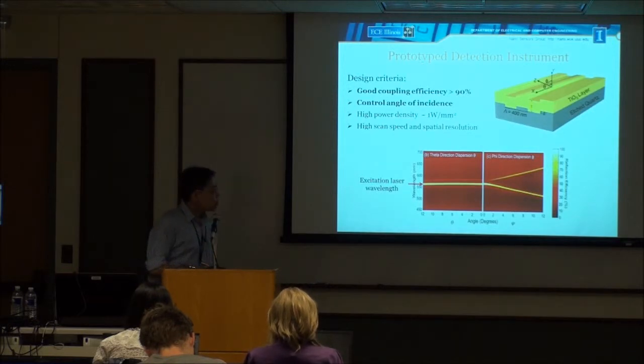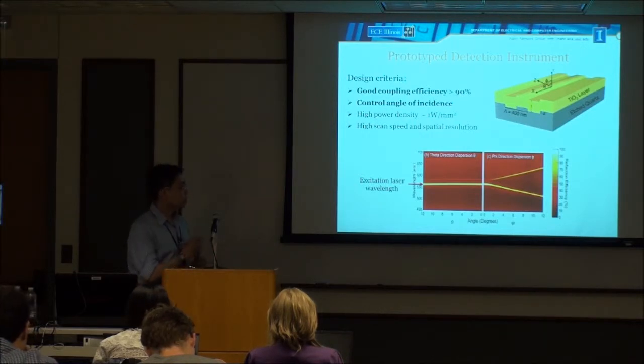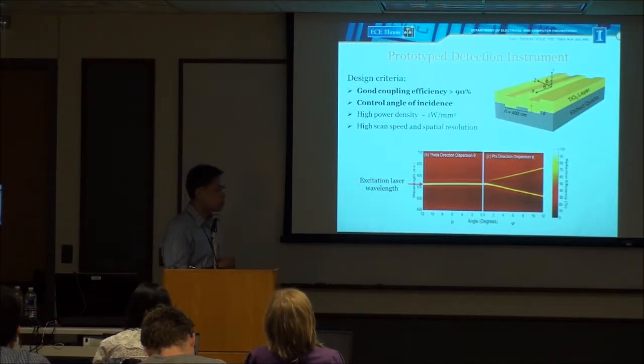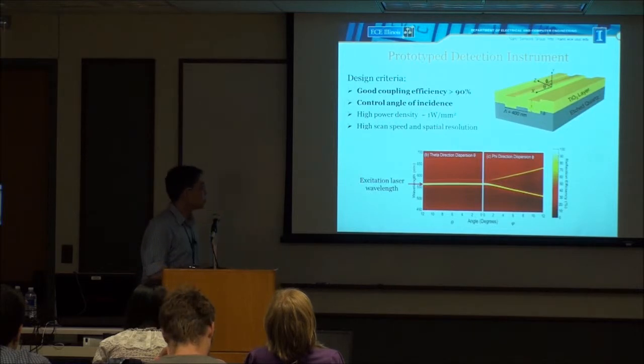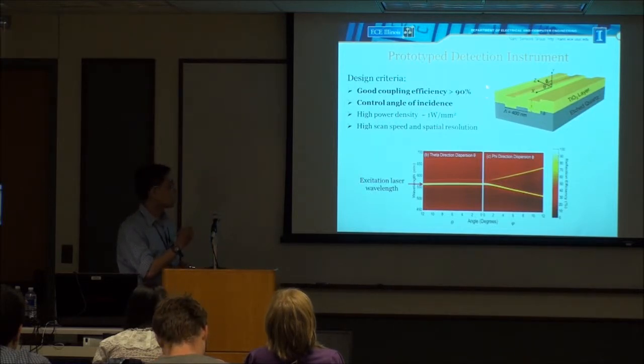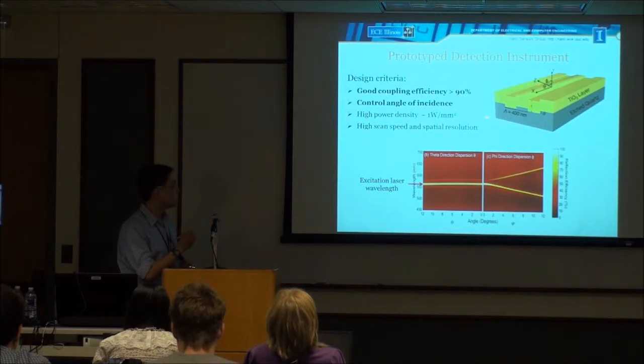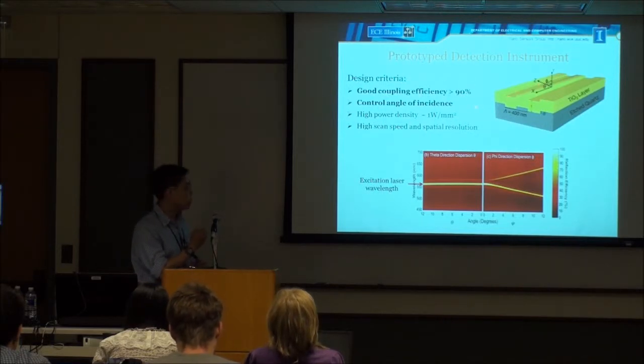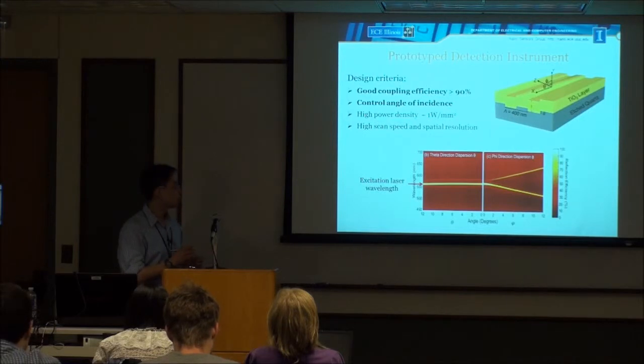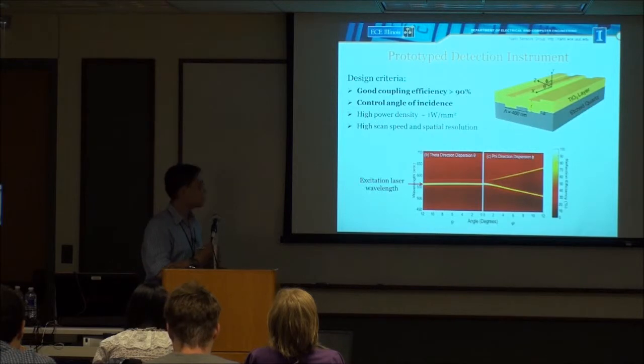So the optical response of our structure is very sensitive to the angle change when you illuminate the laser onto the sensor substrate. So it's very important to keep a good coupling between the incident light and the resonance mode of the photonic crystal structure. In order to do so, we prototyped a special detection instrument, which can provide more than 90% coupling between the incident light and the resonance mode. And we can also control the angle of incidence to match the resonance point.